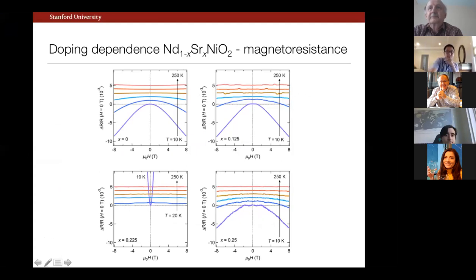Yeah. So I don't think I have here the full anisotropy. Sorry, this is a bit busy, but the bottom line statement is the normal state magnetoresistance is puny. It's very small. So this is, let's say, the undoped compound, x equals 0. And this is, say, the 10 Kelvin magnetoresistance. You can see that this is of order of percent at 10 Tesla.